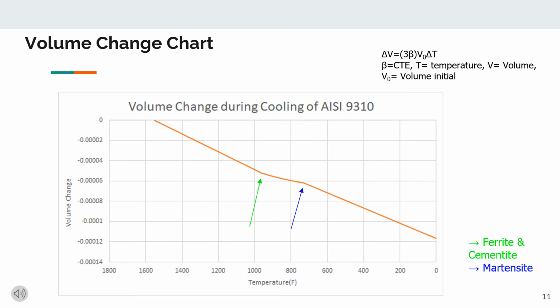Using the equations for the coefficient of thermal expansion and the equation for volume change shown here, we were able to correctly map the volume change during cooling of the AISI 9310 steel. And as we see here, the volume decreases as it is cooled because metals tend to contract as they are cooled.